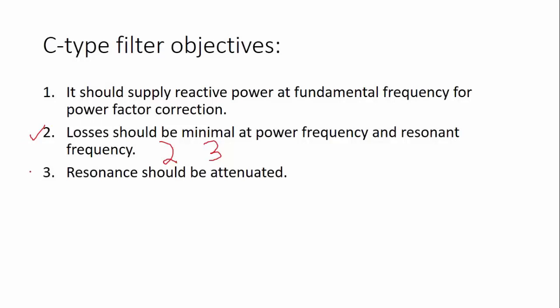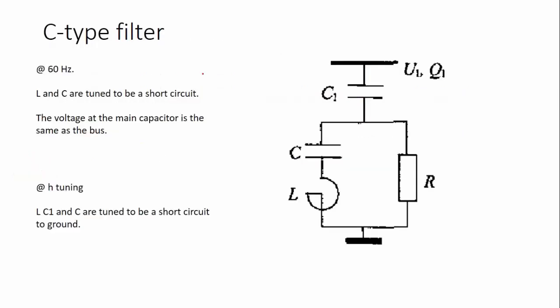And besides, resonance should be attenuated. Otherwise, a notch filter would work, but I don't think the notch filter is a solution. So this is a very important factor on the C-type filters. So some very, very clever fellows came up with this solution. And this is a C-type filter.